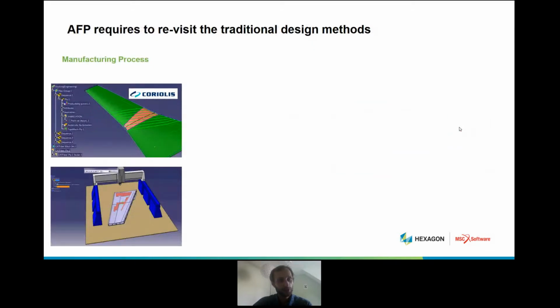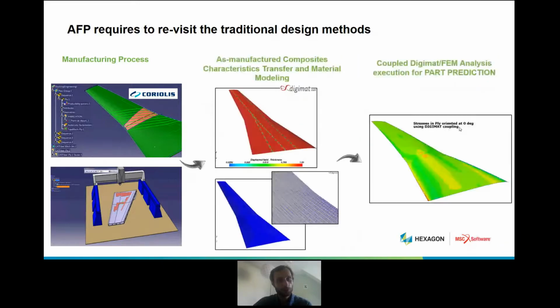So now moving on to the full parts, what we'll witness are the same challenges. So from the manufacturing process point of view, we will know where the fiber is and where the gap locations are, which is a very important aspect because it will drive the local material properties. But also on top of this, we need to know precisely what the local fiber orientation is, which can vary because it's following the actual part's geometry. And so to have an accurate prediction of the part's performance, we need to have this intermediate step where we look at the as-manufactured composite characteristics.